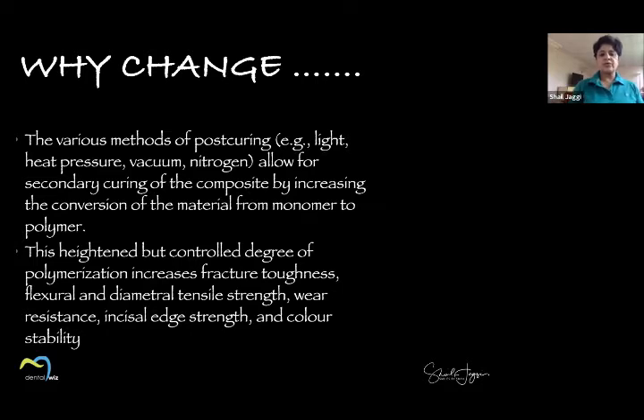The heightened but controlled degree of polymerization increases fracture toughness, flexural and diametral tensile strength, wear resistance, incisal edge strength, and color stability. So again, what I mean by this is if I'm doing most of the procedures extraorally and I'm only using the resin to bond, that's a small component. The complete restoration has better physical properties, better fracture toughness, everything improves. So when I have so many advantages of doing something like this, why would I even want to go ahead and do something like a full crown where I have to work 3 times harder and have half the predictability? But with something like this, absolutely great predictability.